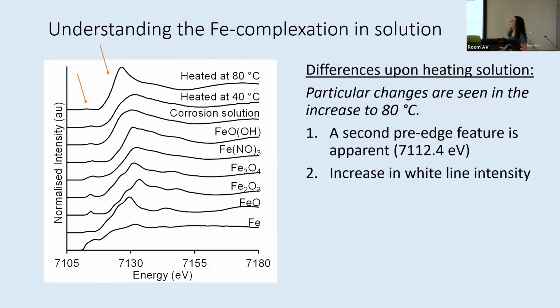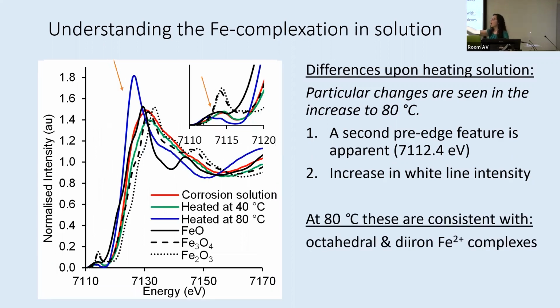So if I go a little bit further, I said I would point out the fact that we heated the solution. One of the interesting things in thinking about this process is also whether or not that complex is affected by the cycling. So in this particular case, given limitations of the system we were working with at the time, we only heated it to 80 degrees. But what's quite interesting is that the heating to 80 degrees resulted in changes, particularly to our pre-edge feature, where we find another node at a little bit lower electron volts, as well as an increase in our white line intensity. So yes, those are kind of details, but this also implicates the fact that when you create that complex, which is clearly going to occur, as you cycle it through, we're actually going to have a change in the nature of that complex. So it's going to start to move towards an octahedral or a diiron complex.